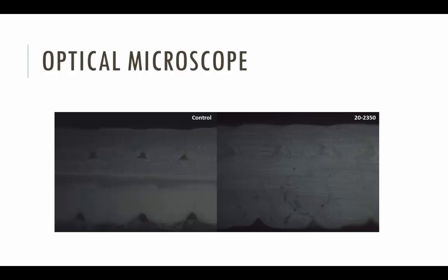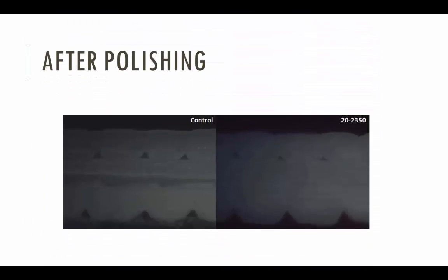The sample was brought back into the lab, and a polishing wheel was used to clean the cross-section of the print. It was re-examined under the microscope, and the new image was much more clear. Visually from the image, we can see that the air gap seems to be reduced, which was a turning point for the project since all the previous data did not support this.